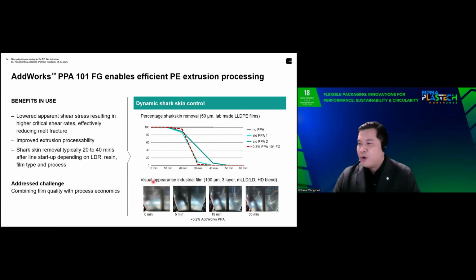In the real process at the customer's site, we also have a reference photo. We produced a 100 micron film with a 3-layer structure, with the composition varying the dosage of metallocene LLDPE. Here at 0.2% or 2,000 ppm of the product, in the beginning, the bubble transparency is not good. After adding it for 5 minutes, 15 minutes, and 30 minutes, the bubble becomes clearer, and the transparency looks good at 30 minutes.